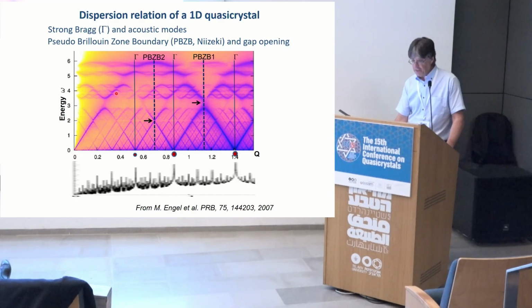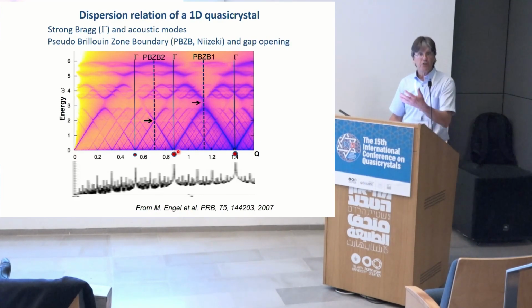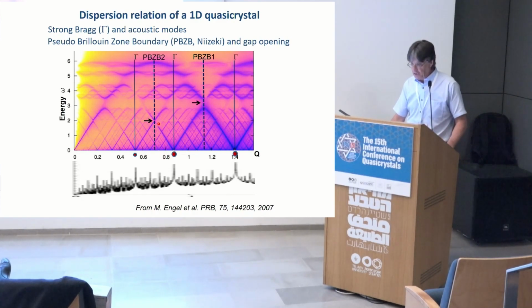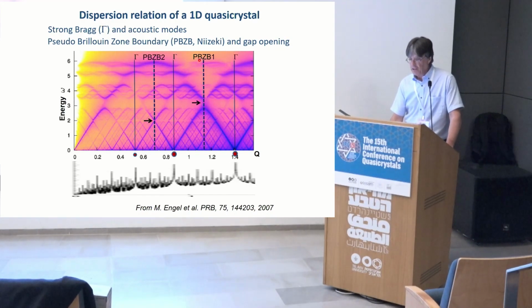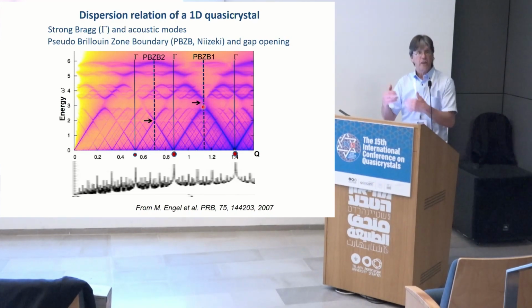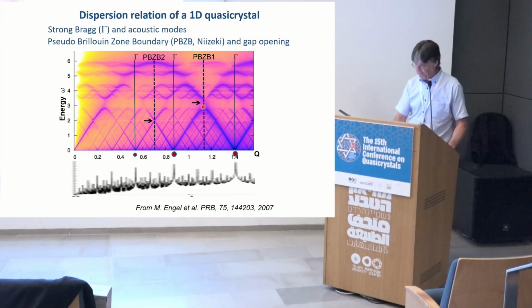And what is shown here is the inelastic neutron scattering measurement that you would do on a Fibonacci chain. And you clearly see that you have branches starting from the strong Bragg peaks with gap opening, and the gap opening is stronger when the Bragg peak in between is very strong. So you have a large gap here, a smaller gap here, and of course you have an infinite number of gaps. But if you take the pseudo Brillouin zone boundary, you clearly see that you can somehow explain what's going on.